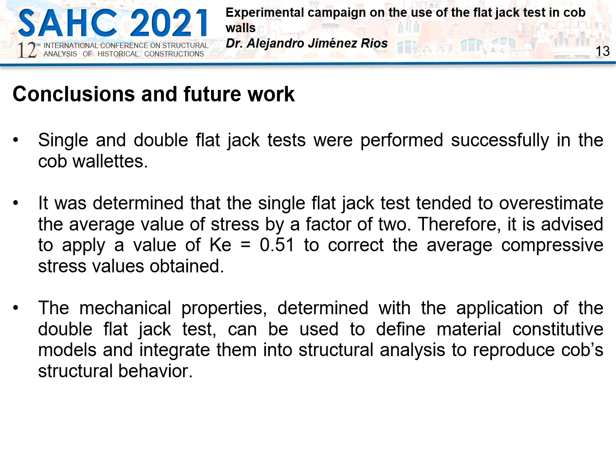From this experimental campaign, it could be concluded that both single and double flat jack tests were performed successfully, that the single flat jack test tended to overestimate the average value of stress by a factor of 2. Therefore, it is advised to apply a value of Ke of 0.51 to correct the average compressive stress values obtained. And finally, that the mechanical properties determined with the application of the double flat jack test can be used to define material constitutive models and integrate them into a structural analysis to reproduce cob structural behavior.